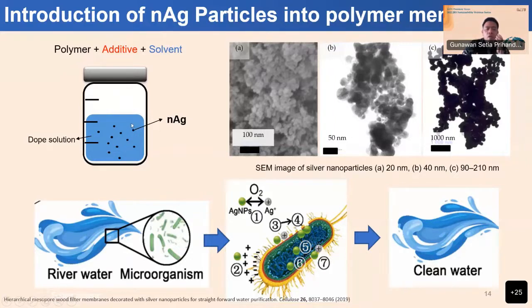And then the same method is used to make the membrane, with phase inversion: just cast onto the glass slide, control the thickness, and then put it in the water bath at a certain temperature. Actually we can also control the pores of the particle by controlling the water bath. But at this time, we just use a normal water bath, at 28 centigrade.